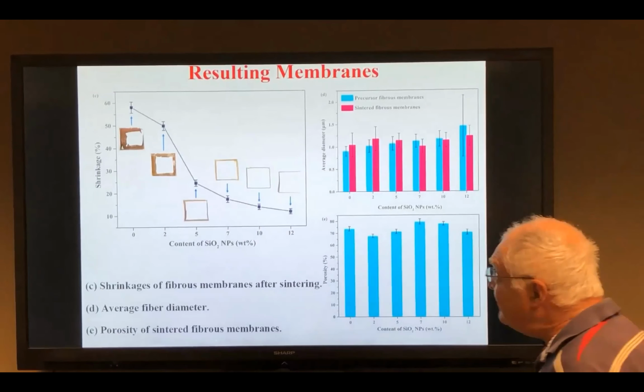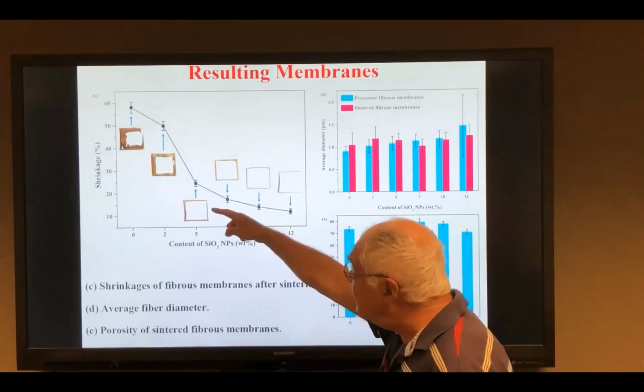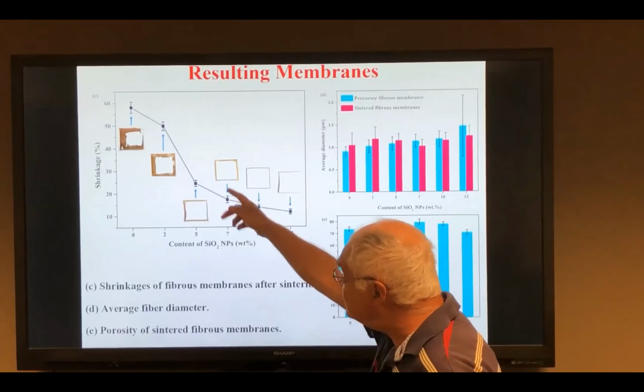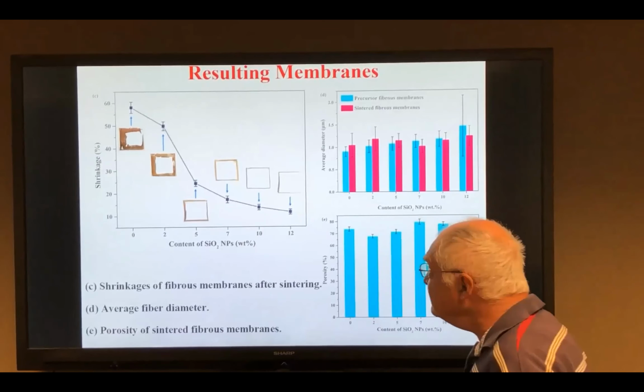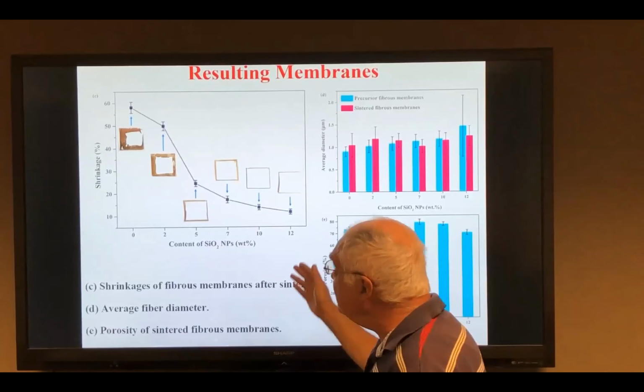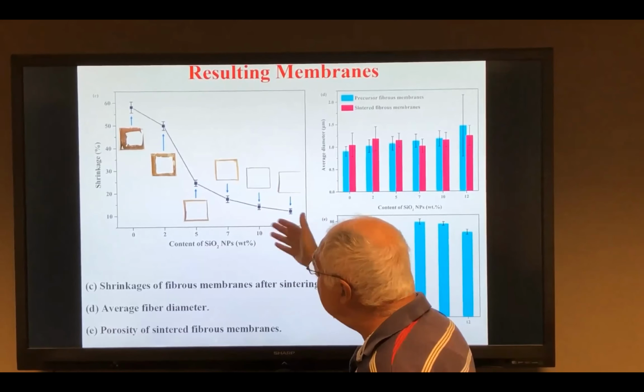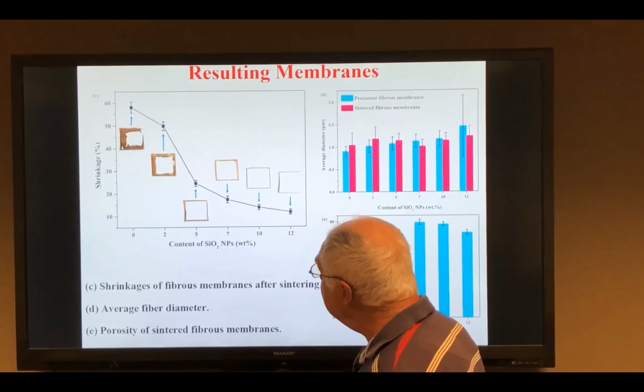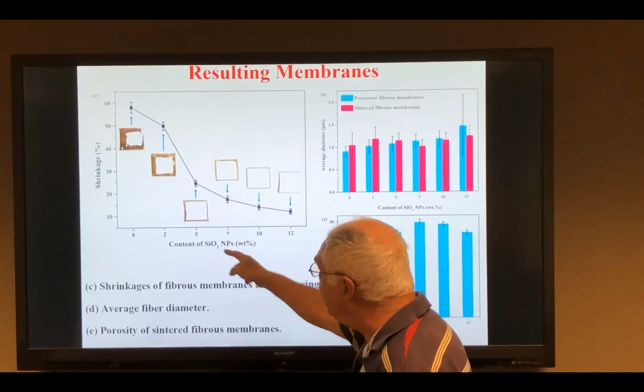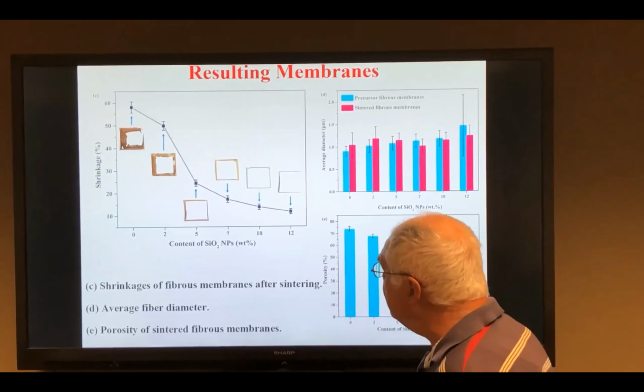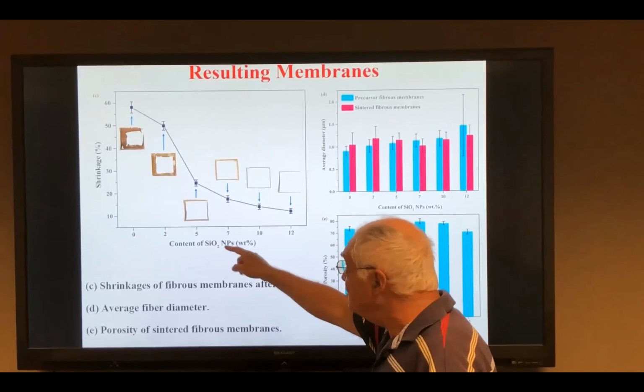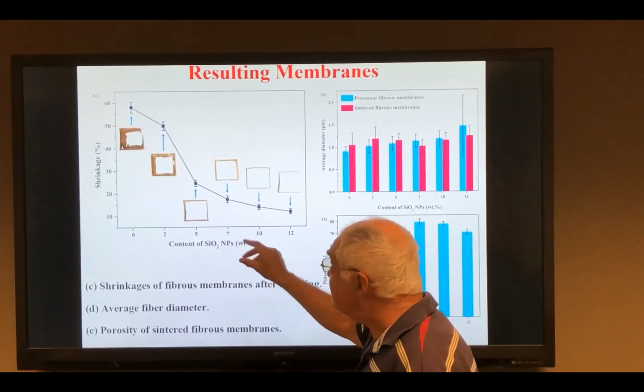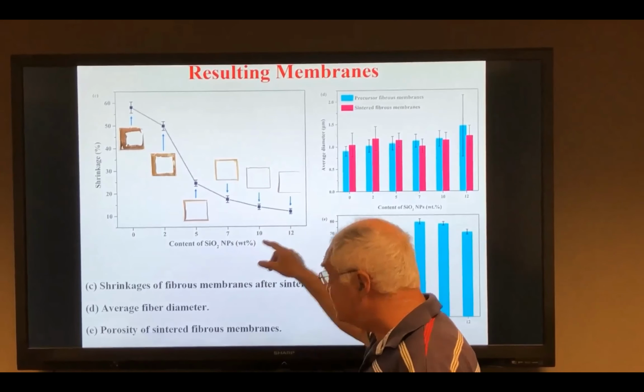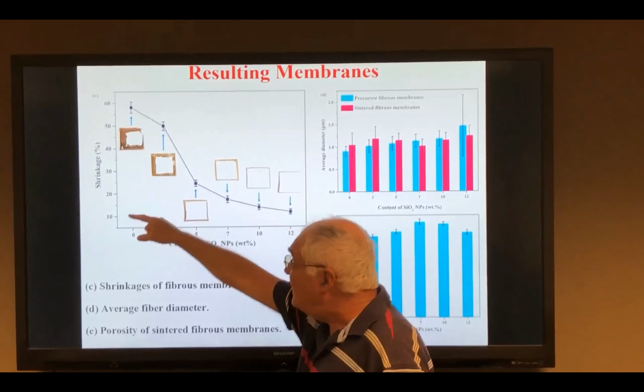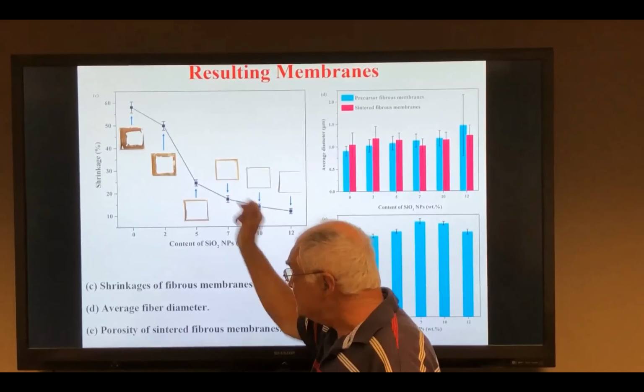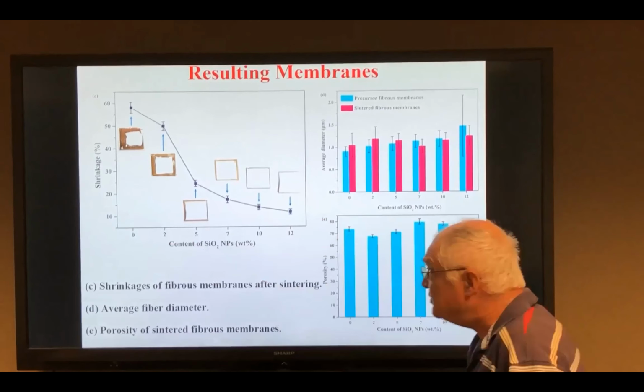Now, as I told you, fibers shrink during the sintering, and you should expect a reduction in mass, and a certain content of glass beads can reduce this shrinkage. So, for example, with more glass beads, you have shrinkage only by 10%. With less, you have up to 60%.